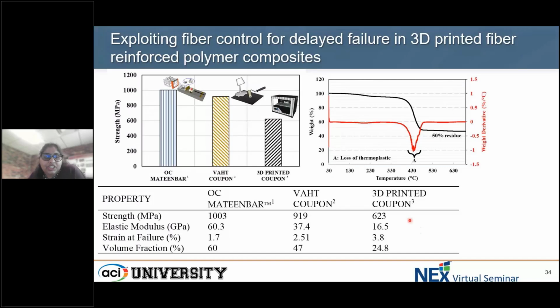Just looking at traditionally manufactured specimens, if you look at a Mateen bar, Owens Corning is the manufacturer of many FRP bars, rebars for civil engineering and construction uses. An OC Mateen bar is about 1000 MPa strength. Its process of manufacturing is very different. Achieving different fiber orientations is not possible, I would say, at this point in an OC Mateen bar or a pultrusion technique, which we use basically to produce these bars.